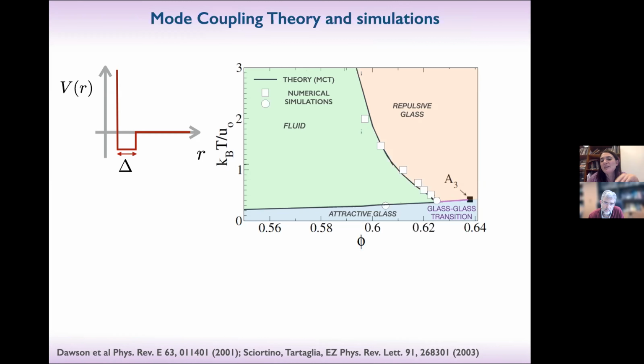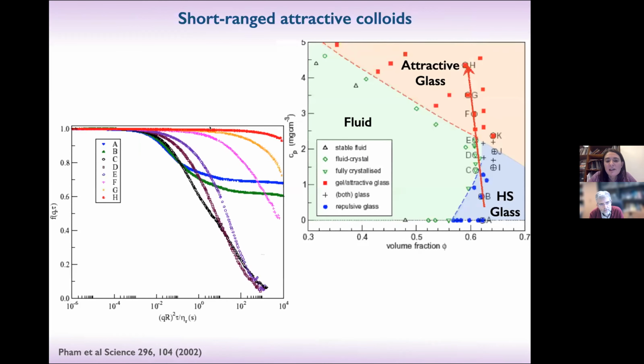And so what happens is that in the end, if you are in the attractive glass and you wait a lot, then these kinds of lines, not this one of the experiment, but in a simulation, would tend to go towards the topological cage, because in the end you are always able to relax the bonds, but you will never be able to break the topological cage if you are at too high a packing fraction. So it's a complicated thing that I didn't discuss with you due to lack of time. But in any case, you find the logarithmic dynamics in this crossover as well.